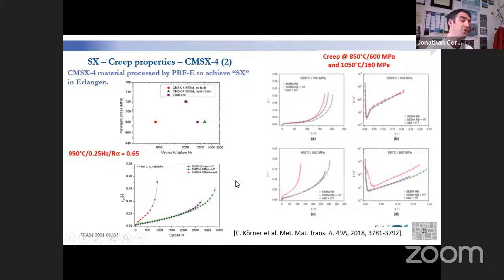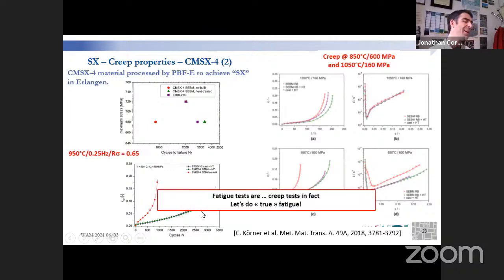And from the work they are doing in Germany, within the very large program called the Transregio SFB 103, from atom to turbine blade, they have been characterizing, in collaboration with the University of Bochum, creep properties and also low cycle fatigue properties. Here you can see that creep properties are very similar to conventionally processed material as soon as solution heat treatment has been performed, so not really surprising. You can see creep properties at 1050 C, 160 MPa, and 850 C, 600 MPa. And here some low cycle fatigue properties at 950 C, 0.25 Hertz, but at a very high stress ratio, meaning that overall those low cycle fatigue properties are mainly controlled by creep damage. So it's not really a true fatigue test.